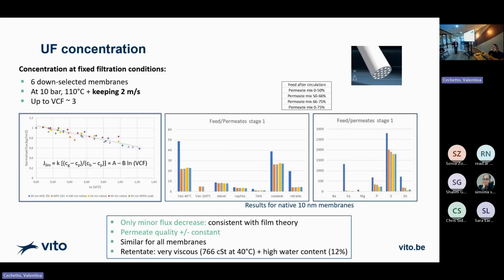With these pre-selected membranes, we did, of course, the full concentration track. In our process, we want to do a full concentration and go with the UF permeate to the ME, the membrane extraction. So we tested 6 membranes here, and as long as we keep the cross flow at 2 meters per second, the flux decline is rather nice. And we can even model it. It's consistent with film theory.